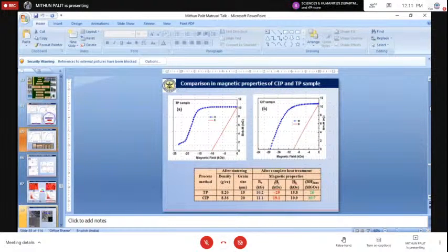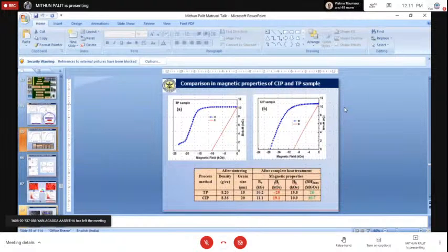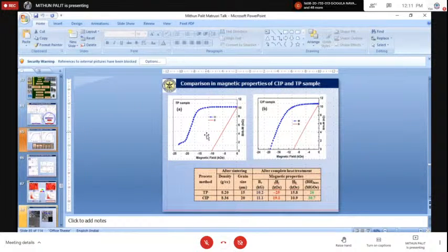The point I want to drive home is that here also, if I compare a magnet processed through the conventional PM route, which is on the left side, with a magnet processed through the cold isostatic pressing route, which is shown on the right side, you see in the right side plot you have less coercivity. However, it has higher Br and more energy product. Whereas in the left side plot, we have more coercivity, but lower Br and lower energy product.